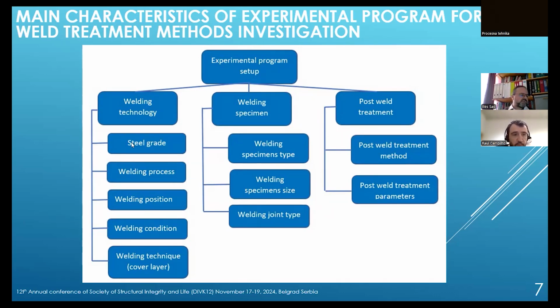Basically, of course, it is influenced by the steel grade, the welding process, the welding position, and the welding conditions. Also important is the welding technique, what I am calling the cover layer, because for heavy plates it is a multi-layer technique, and not only between the material and the weld metal do we have a weld toe. Also, we have weld toes between the layers, which also has an influence on the fatigue life.